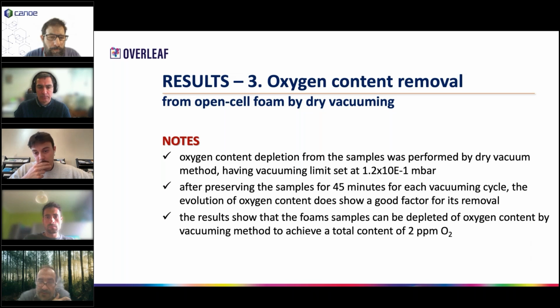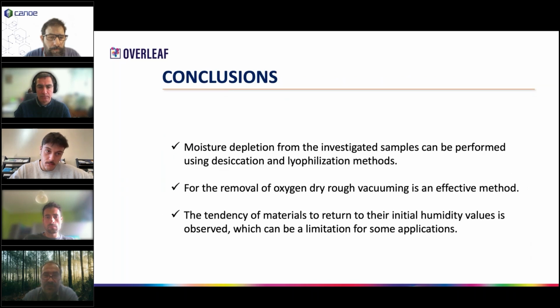Also, it can be noticed that the foam samples can be depleted of oxygen by vacuum down to values below 2 ppm of oxygen. As conclusions, moisture depletion from the samples can be performed using desiccation or lyophilization methods. For the removal of oxygen, it is well known that dry rough vacuum is an effective method, with some limitations due to the specifics of our project.